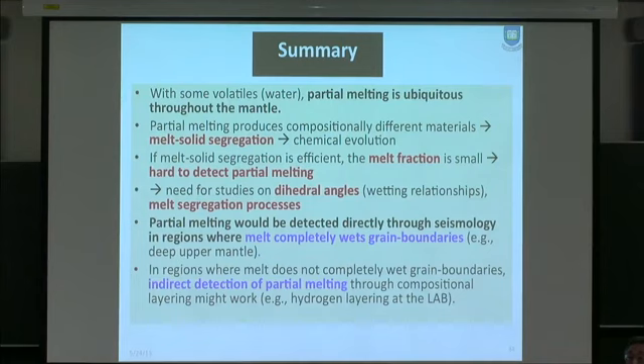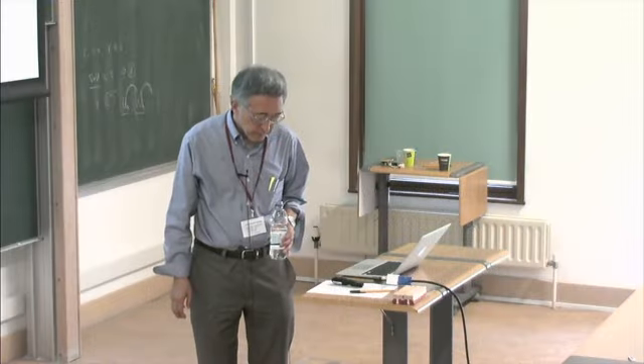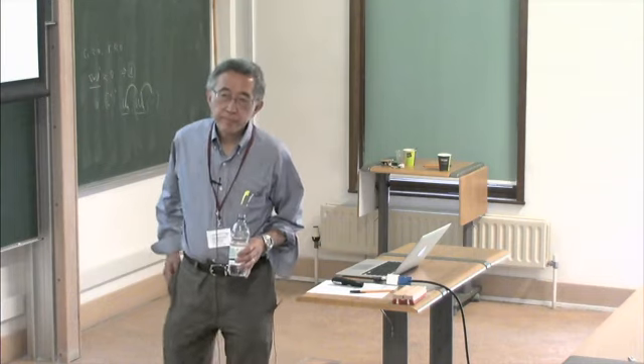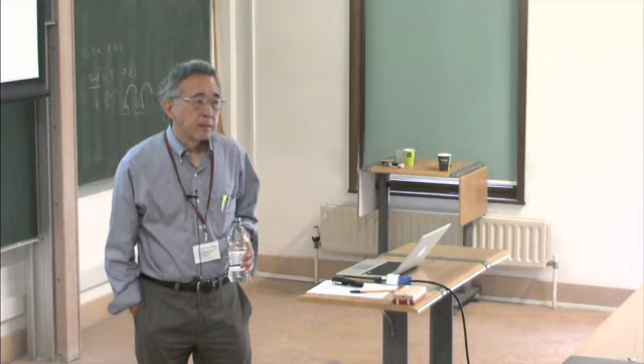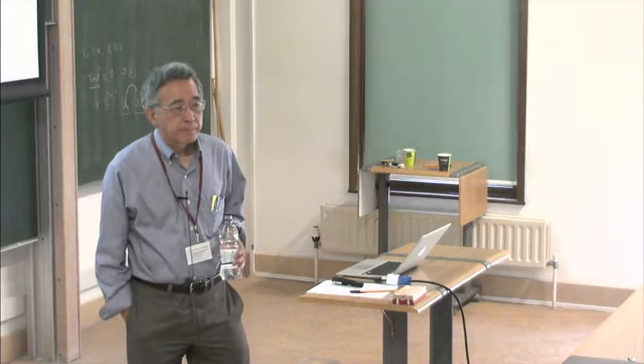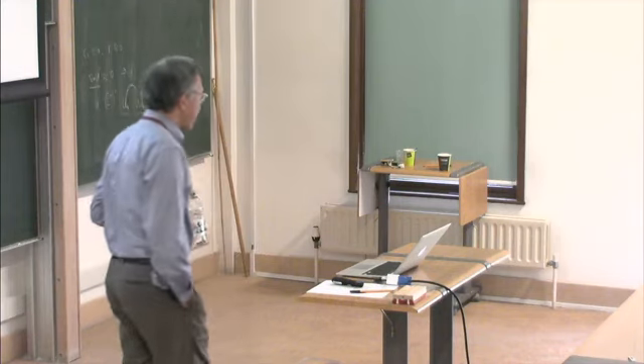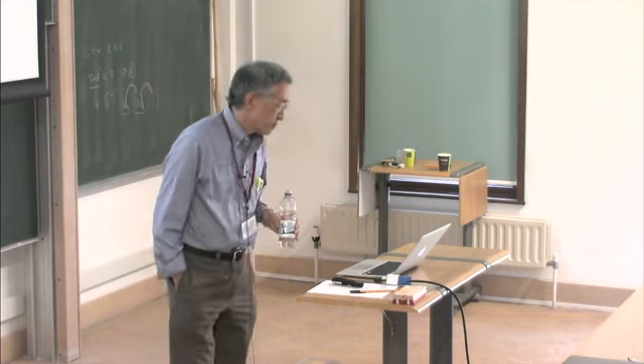Questions for Shun? Rich? I have a couple of questions. The first one is about the density differences. You showed a solidus for the deep mantle which had a positive slope. As you increase the pressure, the temperature of melting increases. And then the argument of having a denser melt, is that consistent with the Clapeyron equation?